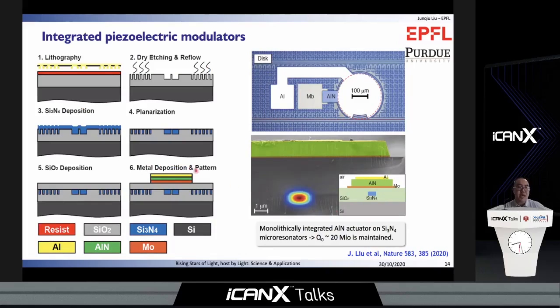in which we built an integrated acousto-optical modulator on a silicon nitride photonic circuit. This result was achieved from a fruitful collaboration with Professor Sunil Bhave's group at Purdue University. This is the fabrication process flow. Here, we build a piezoelectric aluminum nitride modulator on our Damascene silicon nitride photonic circuit. Aluminum nitride is widely used in the MEMS community for microwave and RF oscillators and filters. This is the optical micrograph showing the disc-shaped aluminum nitride modulator covering the silicon nitride waveguide. And this is the SEM image showing the sample cross-section.